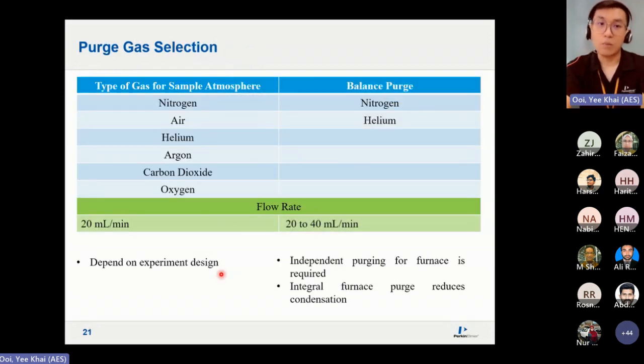So the type of gases that we normally use for sample, you can use nitrogen, you can use air, you can use oxygen, but for balance always nitrogen or helium, meaning only inert gases, okay? Now, flow rates, 20 mL per minute. For balance, usually we recommend double, so as to force every gas that's coming out from the balance chamber, from the sample chamber, to go unidirectionally to the exhaust, okay? Because the purge will happen from the balance, go down to the sample or the furnace, okay?